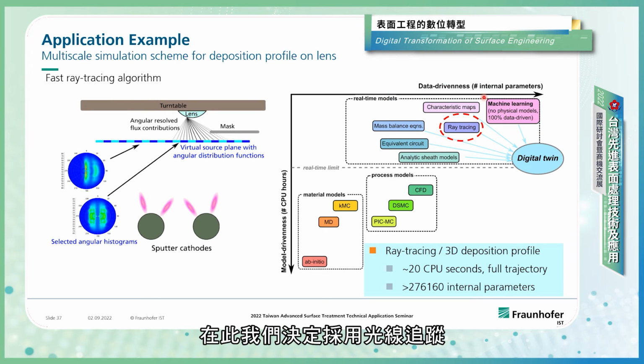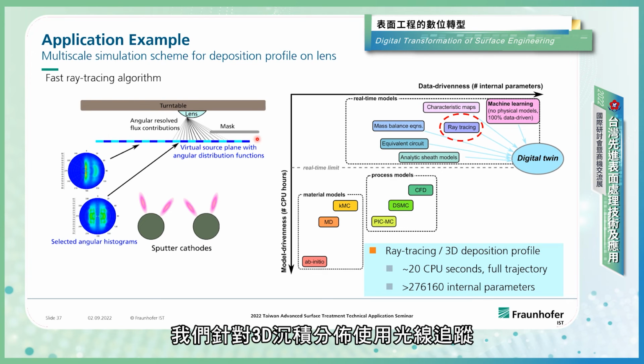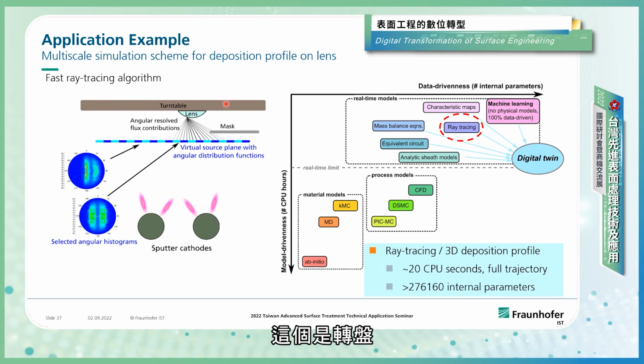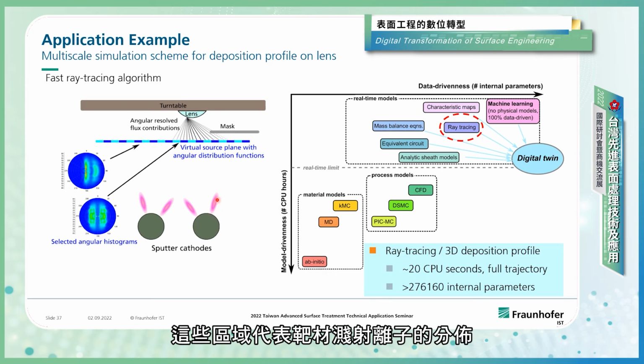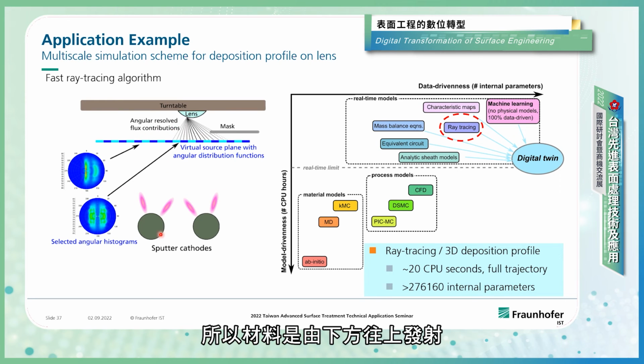And in our case, we decided to go with ray tracing. We have a ray tracing for a 3D deposition profile. Here we have our turntable. We have a big disk, a big table that is rotating, and the lens is mounted on the lower side of the turntable, and we have some sputtering sources indicated here with the circles, and the areas here indicate where the material is distributed. So we will have some material coming from down here up in that area.